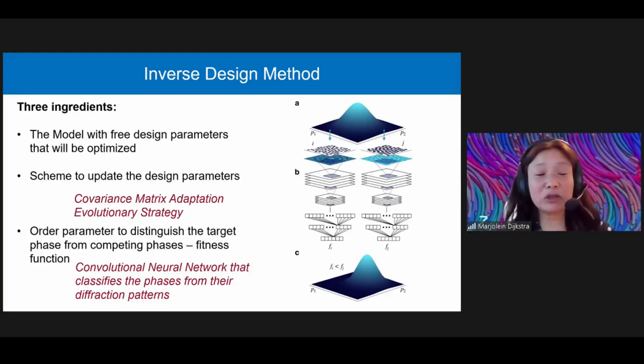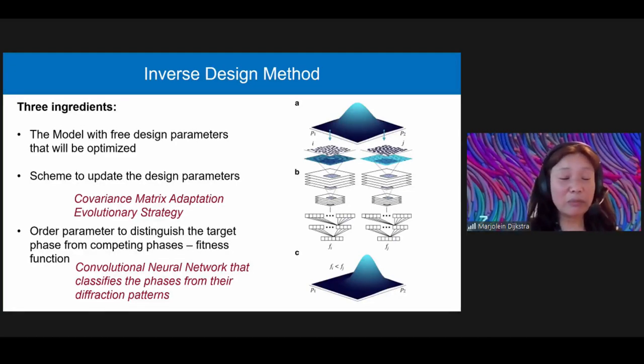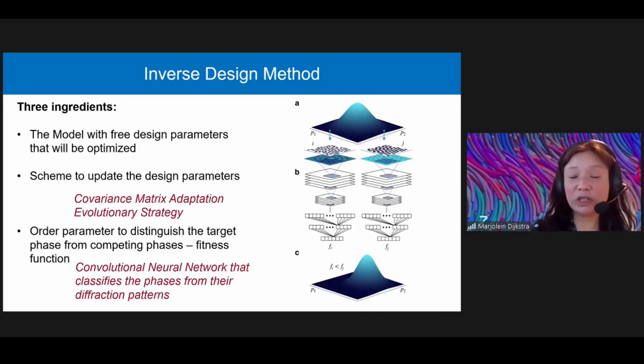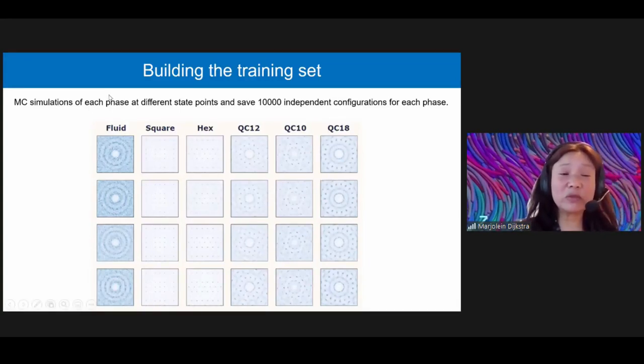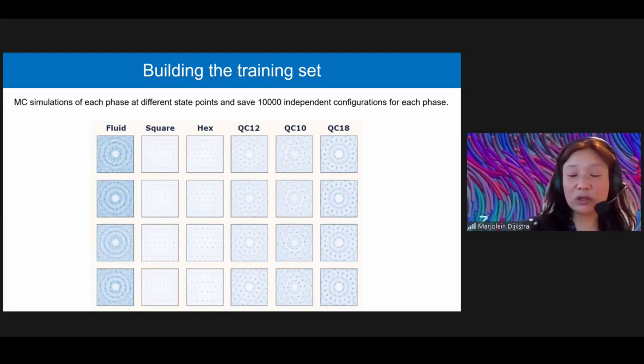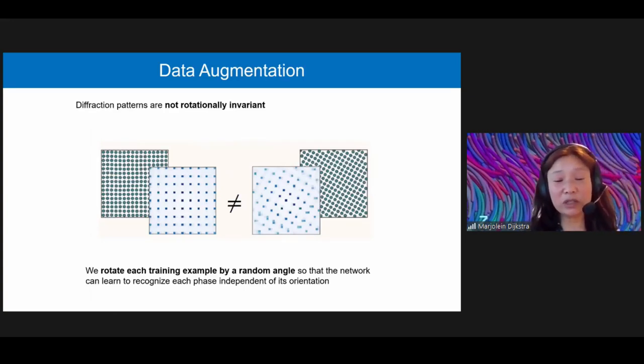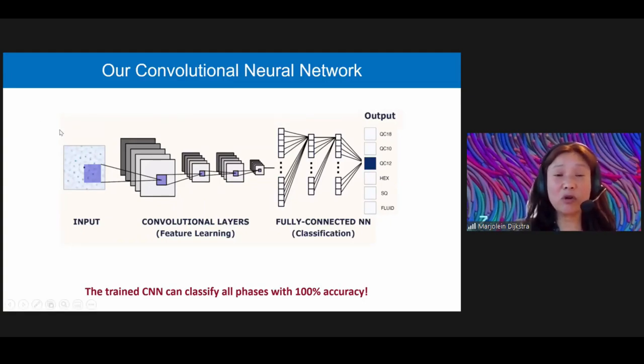The order parameter that is able to distinguish the target phase from the competing phases is based on the diffraction patterns. I already told you that quasicrystals can be identified by their diffraction patterns because it gives Bragg peaks, but with a rotational symmetry that is forbidden for a crystal phase. And we use a convolutional neural network that can classify these diffraction patterns. For that, we perform simulations for the fluid, the square, the hexagonal phase, and the 3 quasicrystals. We save 10,000 independent configurations. We calculate the diffraction patterns, and then because the diffraction patterns are not rotationally invariant, we also rotate them by random angles, such that the network is able to learn to recognize each phase independent of its orientation. And so we use it for our convolutional neural network.